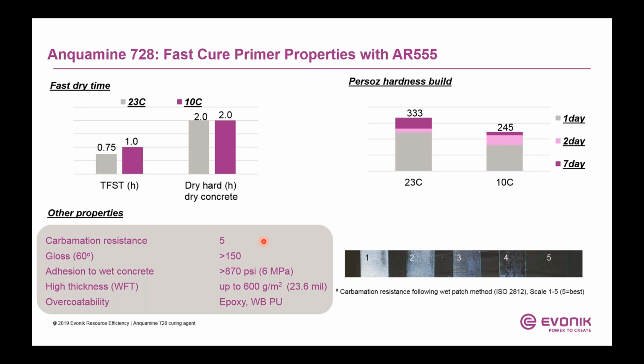So the primer here has excellent carbamation resistance and also shows very high gloss. And very importantly, it has good adhesion to wet concrete substrate. In addition, one of the features of this primer is we can coat it in pretty thick coating in one pass. And it has good overcoatability to epoxy and waterborne polyurethanes.